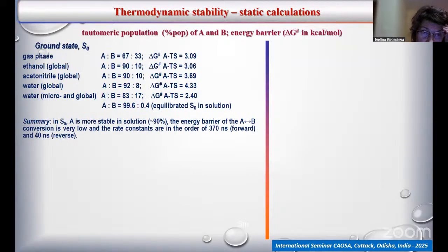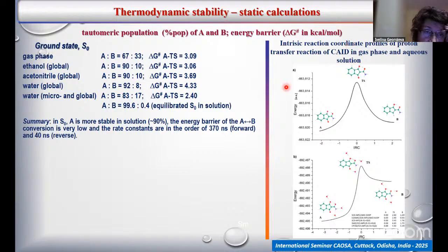So first, on the basis of the calculations, we predict the tautomeric population of A and B tautomers in ground state. In gas phase, this is the intrinsic reaction coordinate. In gas phase, this is the picture: the relative energy between A and B is small, about up to 1 kilocalorie per mole, and the corresponding tautomeric population is 67 for A and 33 for B. The energy barrier was estimated to be about 3 kilocalories per mole.